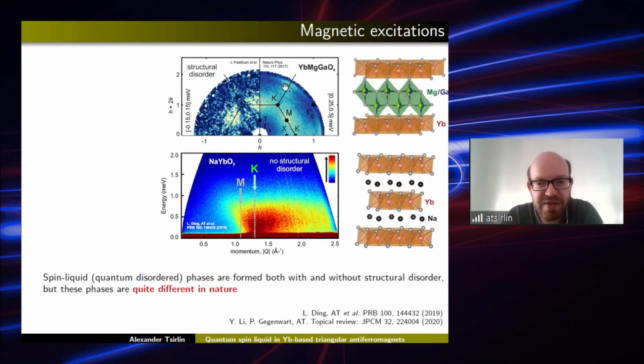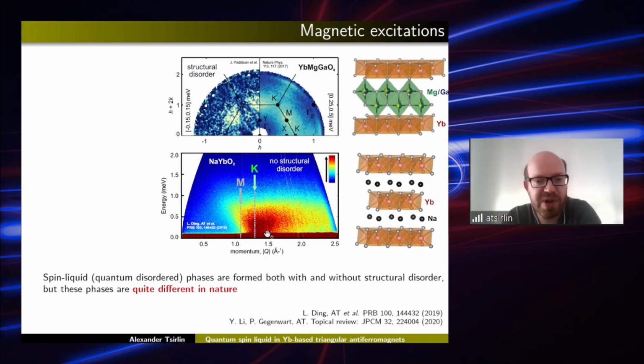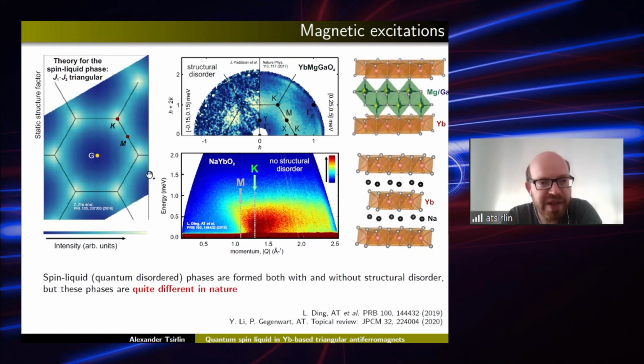You see that it's actually different in the compound with the structural disorder and in the structurally ordered compound. We have this hexagonal Brillouin zone with the K and M points, and for YbMgGaO4, the intensity accumulates at the M point of the Brillouin zone. For the NaYbO2, the intensity accumulates at the K point of the Brillouin zone. So that's the clear difference between the 2. And if we now look at the theoretical prediction that you see here, so the Dirac spin liquid for some triangular spin model, then the intensity is expected to be at K and not at M.